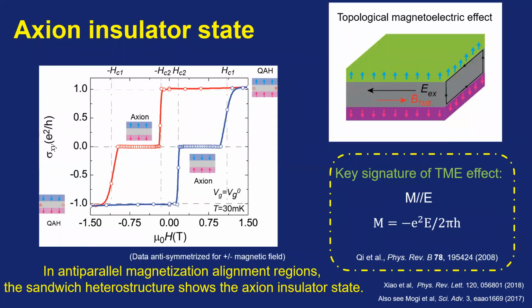So this is the transport result of this kind of axion insulator sample. This is the Hall conductance. This is the magnetic field. At a very high magnetic field, they are parallel aligned. So this is just a quantum anomalous Hall state. This is e squared over h. When you sweep the magnetic field back, because the chromium layer has a small HC, it first reverses the magnetization and forms this kind of anti-parallel alignment. If you further sweep, when the magnetic field is about minus HC2, you will realize this kind of downward parallel alignment. This also becomes a quantum anomalous Hall state.